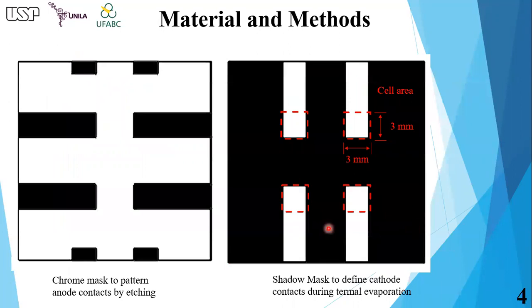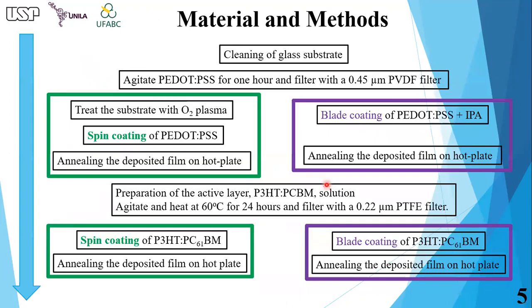To define the organic solar cell contact, we used a photolithography mask on the ITO, which is the anode, and a shadow mask during aluminum thermal evaporation to define the cathode. The sequence of steps for the deposition of the thin films is represented in this diagram. The substrate cleaning process and the solution are the same for both deposition techniques. Substrates used in spin coating deposition need surface treatment with oxygen plasma, while the ones used in blade coating do not.